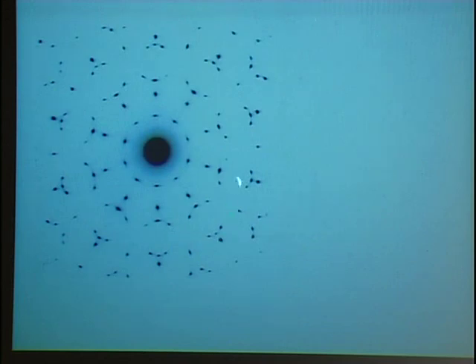But this diffraction pattern is a pseudo 5 or 10-fold rotation symmetry, because each spot here is given by another crystal. This spot comes from one crystal, this spot comes from another one, and it looks very beautiful, 10-fold, but it's really pseudo 10-fold. It's not a single crystal, it's a twinned crystal.